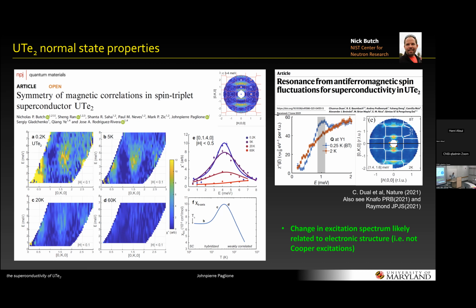The irony is that this is a reported spin triplet superconductor. So the question immediately arose, how do you get an antiferromagnetic resonance in a spin triplet superconductor, which is thought to arise from ferromagnetic interaction? And that was also somewhat answered right away, theoretically, also in the context of strontium ruthenate, that it's possible to do that. But I would raise the question, if this intensity in inelastic scattering is not to do with an antiferromagnetic interaction, then what does it mean?